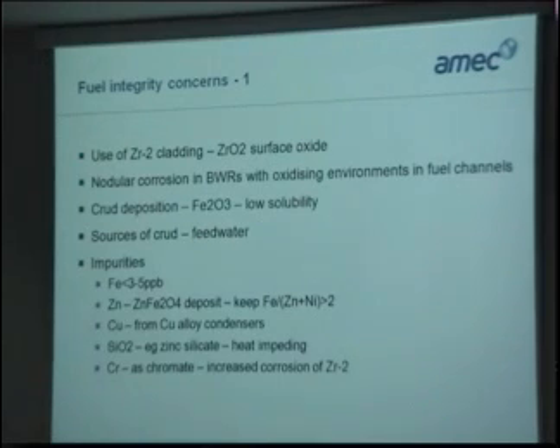On the next slide, there are fuel integrity concerns. Here we don't have the lithium issue, but we do have other corrosion aspects. A phenomenon called nodular corrosion is seen on BWRs in oxidising environments. The oxide layer tends to be Fe2O3 rather than magnetite, and the various impurities are, for example, zinc, copper if you have copper alloy condensers, silica, zinc silicate, silica from the water impurity, and chrome from the steels.